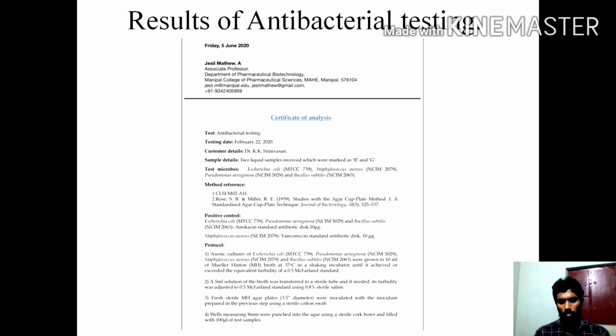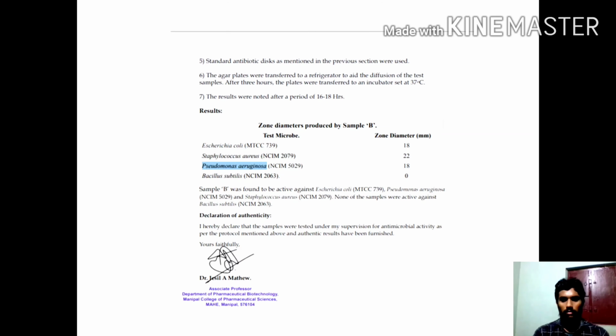Here it shows the protocol under which this test was performed. And here is the result. It shows considerable activity against E. coli, Staphylococcus aureus, and Pseudomonas aeruginosa. As far as Bacillus subtilis is concerned, it's a non-pathogenic bacterium, and it was tested for protocol purposes. However, the zero activity against that bacterium doesn't affect our objective.